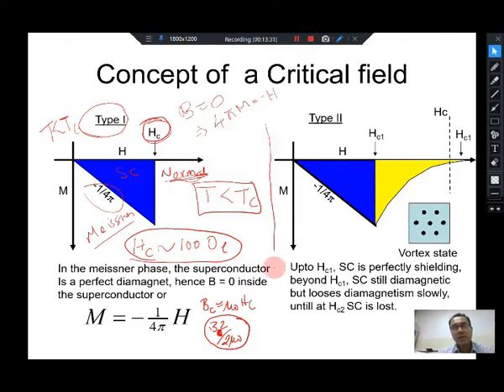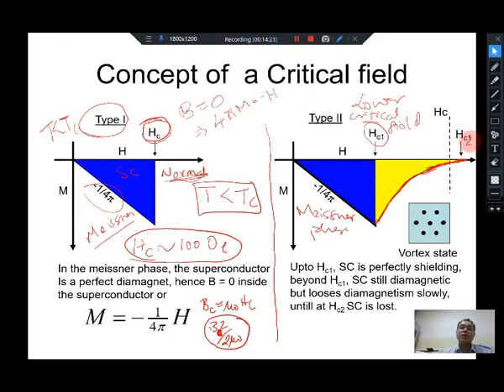But there are other types of materials which are called type 2 superconductors, wherein the magnetization will be Meissner-like, where susceptibility is minus 1 by 4 pi up to a field which is called the lower critical field, which is a few hundreds of Oersted. But once you cross the lower critical field, the magnetization does not immediately crash to zero; rather the diamagnetism decreases very gradually and slowly, and only at very large magnetic field values, I'm sorry, this is Hc2, which is called the upper critical field.